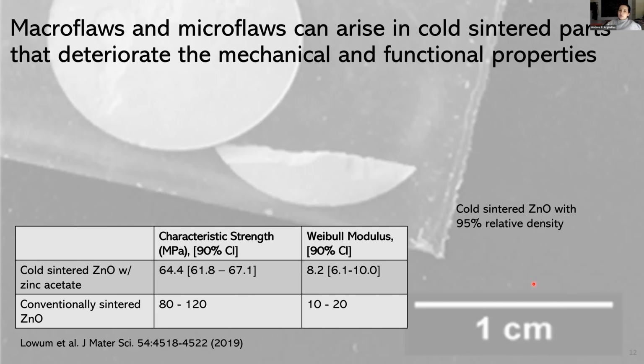So the main challenge here is that we have macro and micro flaws that arise and deteriorate the mechanical and functional properties of these materials. So what I'm citing here is a couple of different things. First, let's talk about the picture in the background. It is a cold sintered part that had a 95% relative density. This is pretty much the standard for what we use to qualify a part as good or bad when it comes to these kinds of sintering processes where you're just generating a bunch of pieces.